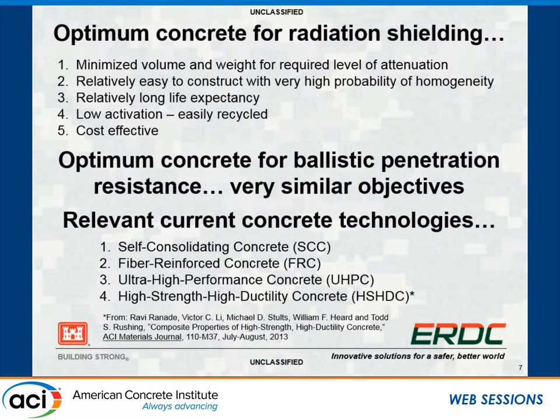What is ultra-high-performance concrete? I'm on the committee for that, and we have a definition out for public comment through concrete terminology. Concrete ultra-high-performance is defined as concrete that has a minimum specified compressive strength of 150 MPa, or 22,000 PSI, with specified durability, ductility, and toughness requirements using reproducible test methods. Fibers are generally included to achieve specified requirements. The key is you specify durability, ductility, and toughness—so you want this concrete inside the dry cask to be durable and tough enough for the radiation and heat.